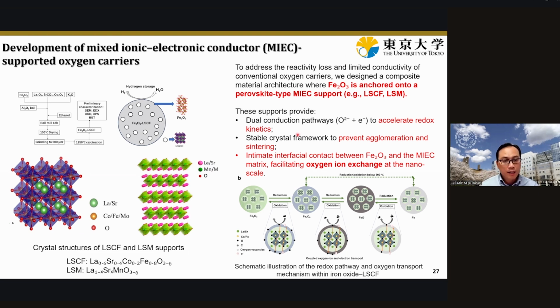And in our study, we can facilitate much better oxygen ion exchange. Finally, we can also reduce the activation energy during the reaction itself, especially during the reduction process. From the experiments, we can confirm that it can also prevent agglomeration, which is very important in our research, because we would like to avoid any agglomeration during fluidization, especially during the reduction, and also the oxidation or the reaction with the steam itself.